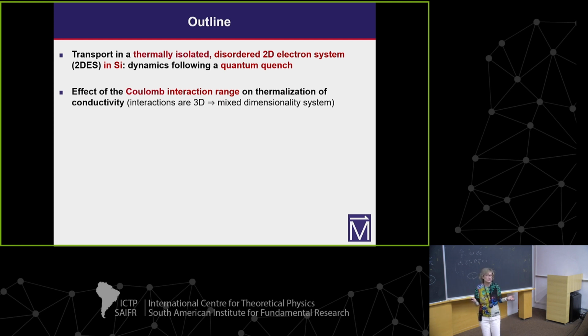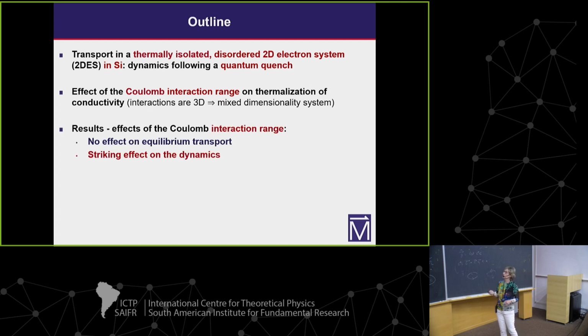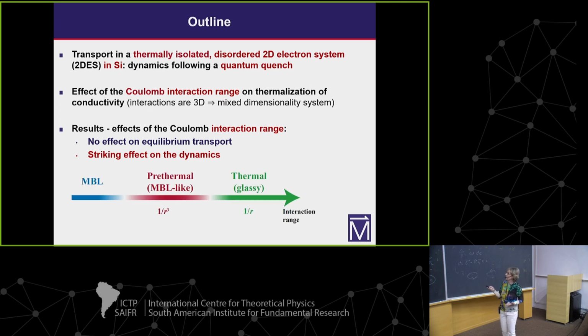I'm going to tell you our results right away, so if you get lost later, hopefully you remember this. We did not see any effect of the interaction range on the equilibrium transport, but we did see a striking effect on the dynamics. In particular, we found that in the case of a long-range Coulomb interaction, the system does thermalize, even though the dynamics is glassy because of the frustration in the system.